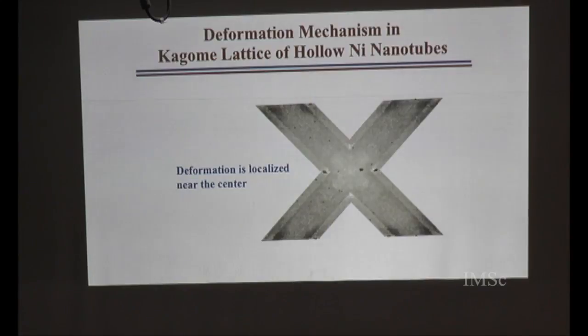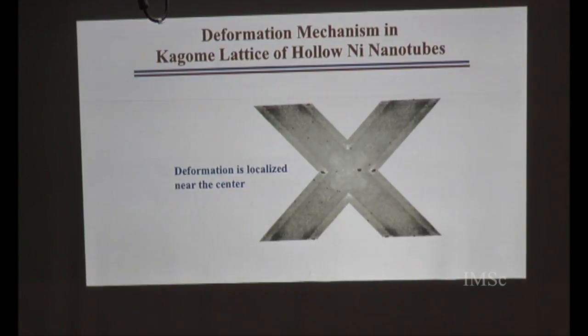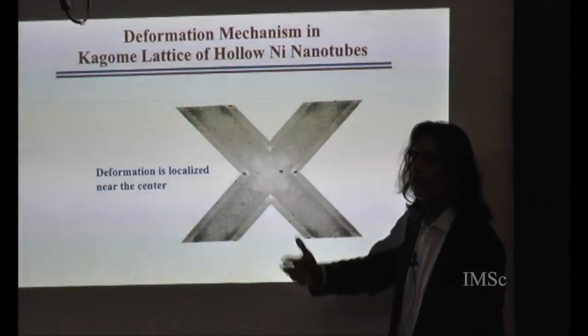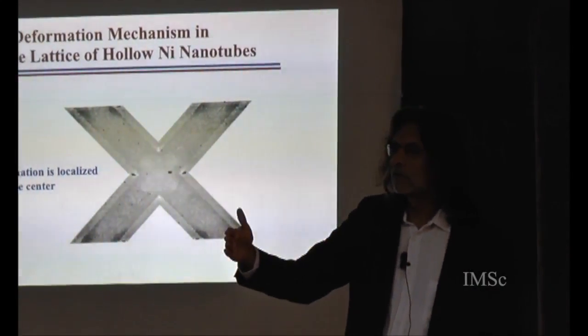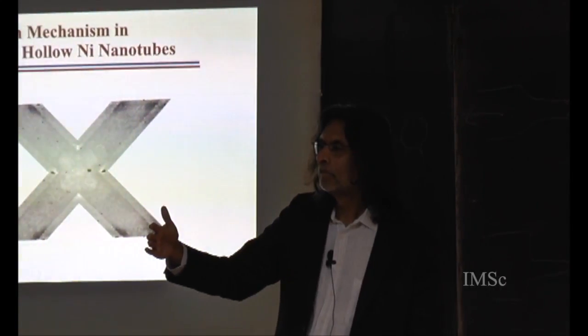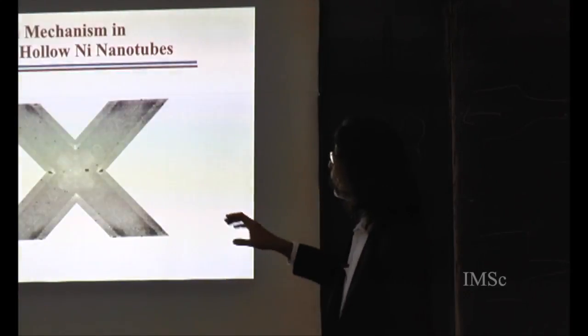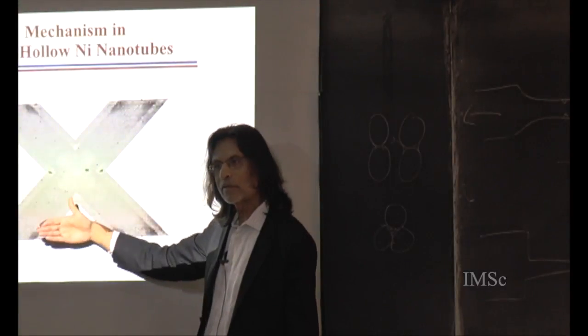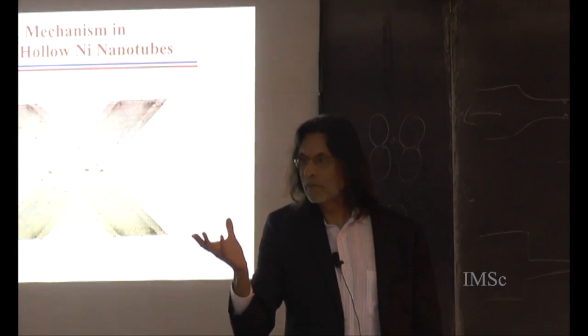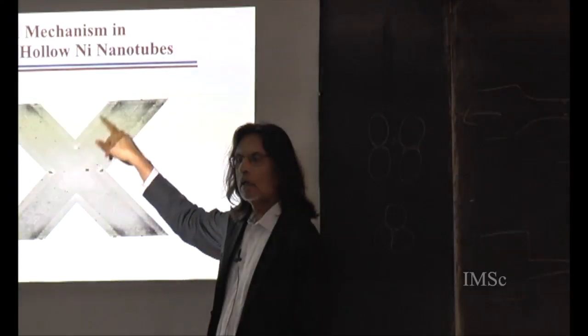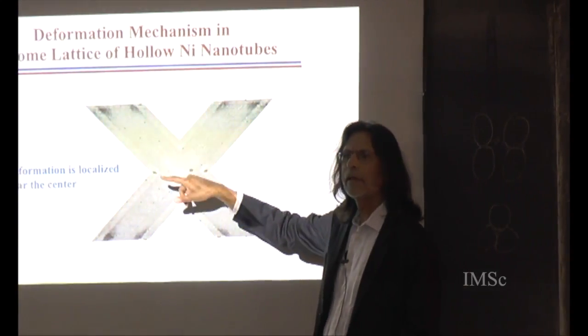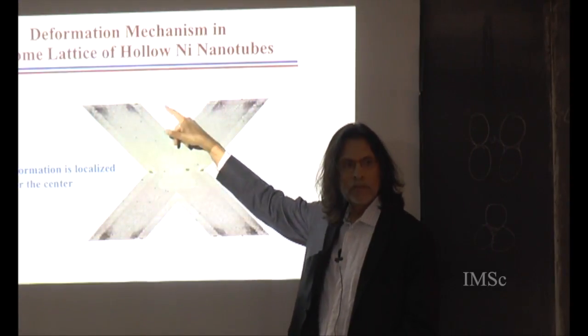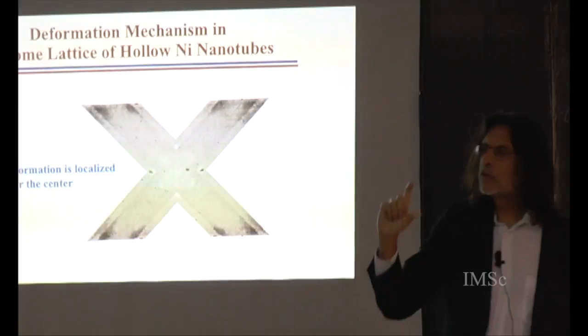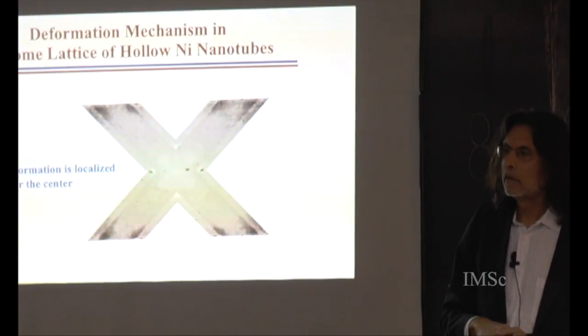Where is the Kagome lattice? Sorry? Where is the Kagome lattice? This is a cross section of the Kagome lattice. But I can't see any Kagome lattice. The reason you're not seeing it is that I'm just showing you a cross section, but it is a three-dimensional structure. What scale? These things are 70 to 100 nanometers in length, each one of these legs. Each nanotube is between 70 to 100 nanometers.